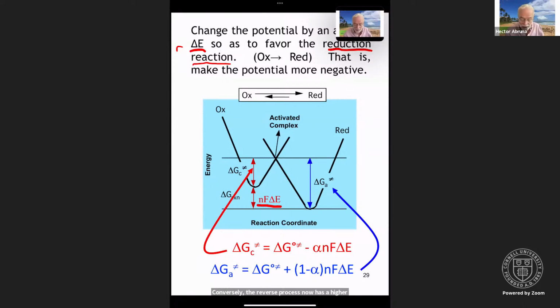So now you see that there's a very big difference between the location of the minima in these parabolas, basically because we decided to change the potential. And so the change in the activation free energy for the forward or the cathodic or the reduction process is the standard one, which is what we started off with. And we're diminishing this by nF delta E that comes from the potential and a fraction of that, alpha.